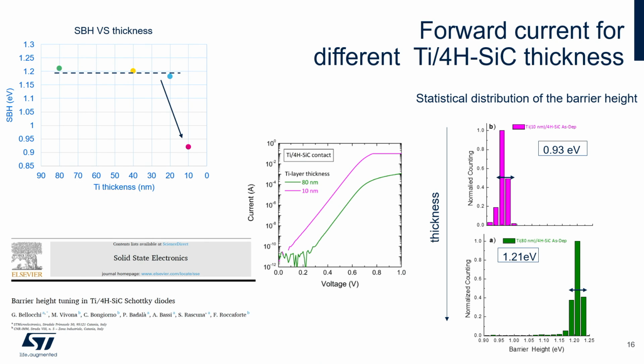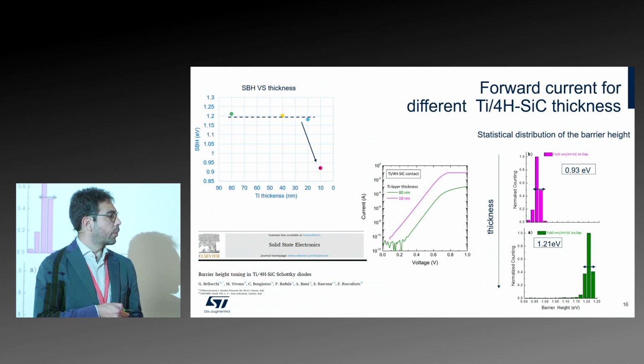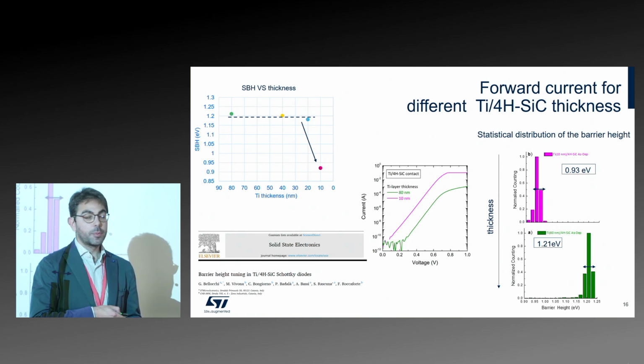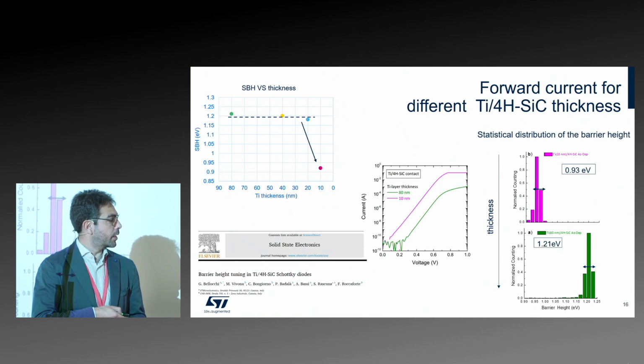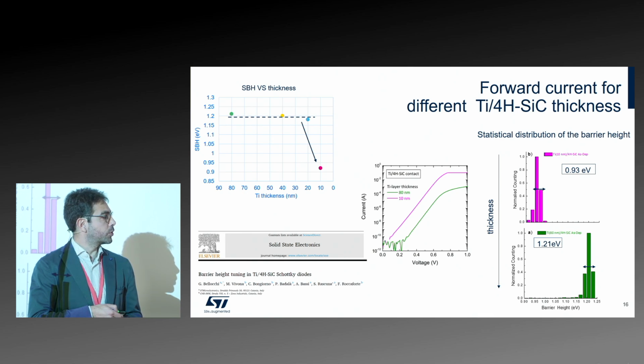And this makes sense because the Schottky barrier height depends just on the surface. But at 10 nanometers, I observe a fall down of the Schottky barrier height from 1.2, that is the typical value, to almost 0.9, that is really low. I was looking into the IV curve, and the Schottky contact seems to be really good. And again, this is the statistical distribution of the Schottky barrier height along the wafer. If I compare, this is our typical wafer with this width of the statistical distribution, and we have a value of 1.2 for the titanium.